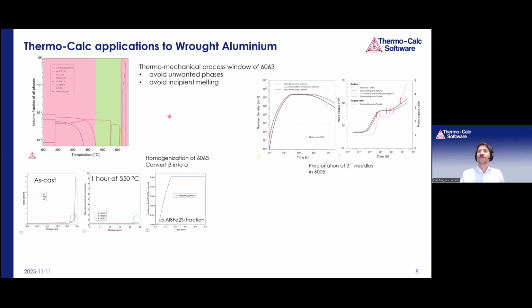And then for wrought alloys, you usually do a precipitation and age hardening treatment at a lower temperature, such as 200 or 180 degrees, and we can simulate this in the precipitation modules here. Now we're looking at a 6005 alloy grade and the precipitation of beta double prime needles. This is a metastable precipitate, and there's a transformation between spherical and needle morphology.